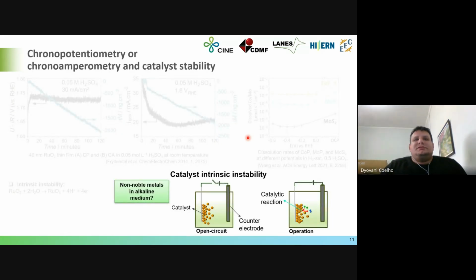This is because mainly the non-noble metals in alkaline medium can be intrinsically unstable. During the open circuit potential, for example, the catalyst can just dissolve in contact with the electrolyte. But during the reaction taking place on the catalyst, the reaction can also trigger the catalyst dissolution. So we need to know what is happening.